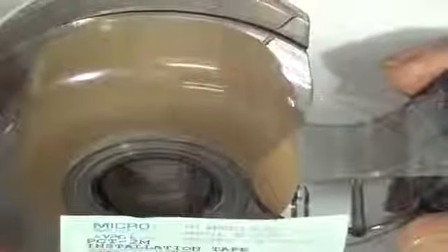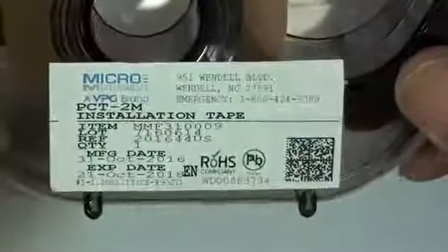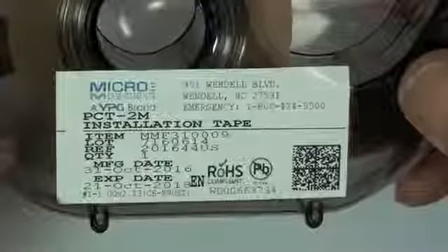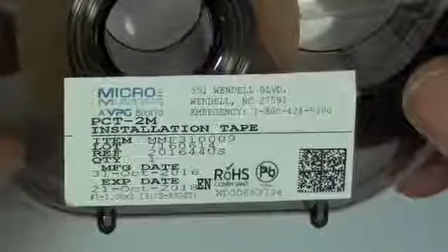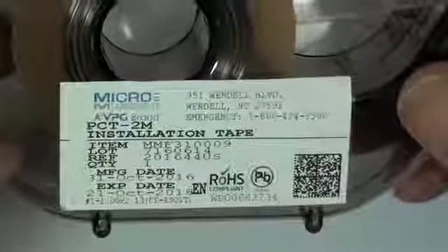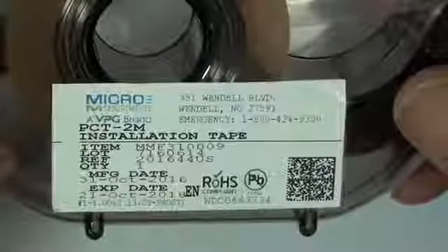Right. It's the right balance of tack. Yes. It's going to be tacky enough to pick up the gauge, but yet be easy to remove. Also, it's very well tested. We know that mastic, the adhesive that's on that tape, is compatible with all the micromeasurement strain gauge adhesives. It can also handle the cure temperature range of any of the elevated curing adhesives. So it's very well tested. That's what makes it special, really. And the tape is also mechanically stable enough to make sure that the alignment remains correct.